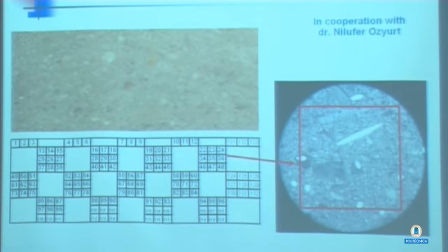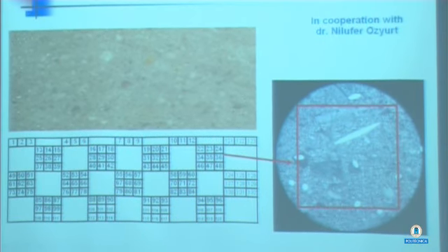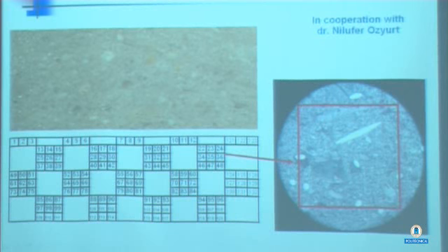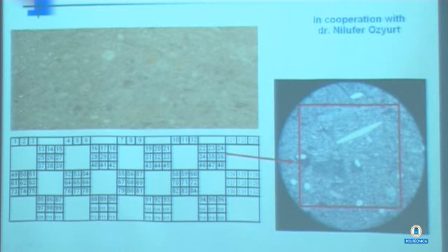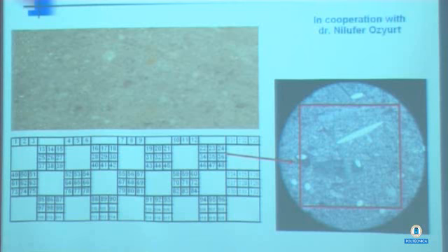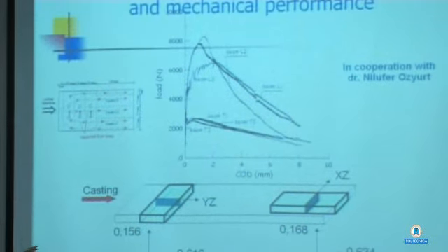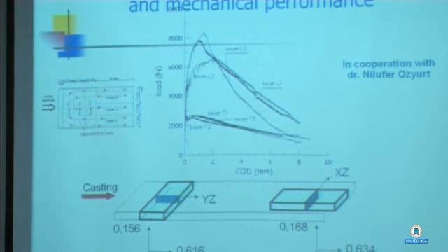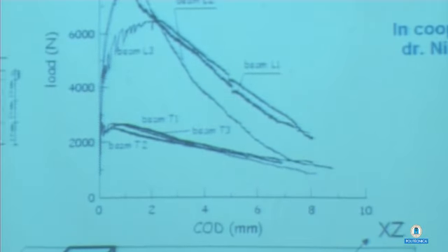You can see there an example. And from the elliptical shape of the fiber cross-section, we were able to calculate the cosine of the orientation angle. Through a statistical method, whose details are in the paper we submitted to Materials and Structures, we ended up calculating orientation density values in this direction, in this direction, and in this direction.